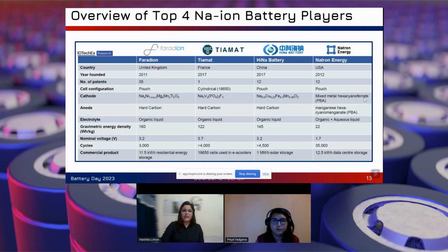Now, if we see the overview of the top four sodium ion battery players, Faradion, Tiamat, Haina Battery, and Natron Energy are taking the lead. The gravimetric energy density is highest right now for Faradion, which is 160 watt-hour per kg. They have a nominal operating voltage of 3.2 volt, and they have reported a cycle life of up to 3,000 cycles.